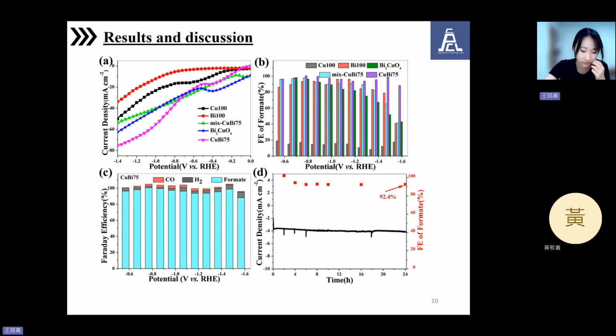In Figure B, we see the FE for formate. Again, CuBi75 stands out with the highest FE for formate, reaching up to 100% at -0.77 V. Compared to other samples like Cu100, Bi100, and even Bi2CuO4, CuBi75 consistently performs better across a wide potential range.